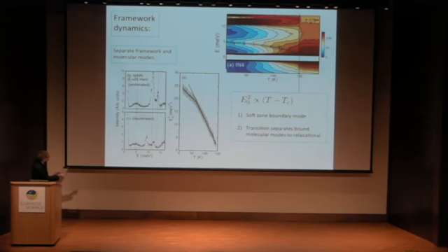So this is a plot of intensity as a function of energy transfer taken on MARI. What you can see is that upon deuteration, when you scan up to high energies, you have these peaks up here that shift and decrease in intensity. So they're associated with the molecular motions. But you have this thing here, which doesn't change at all with deuteration. So this is attached to the framework, this mode at around 5 meV. And these up here are associated with the molecular motions.